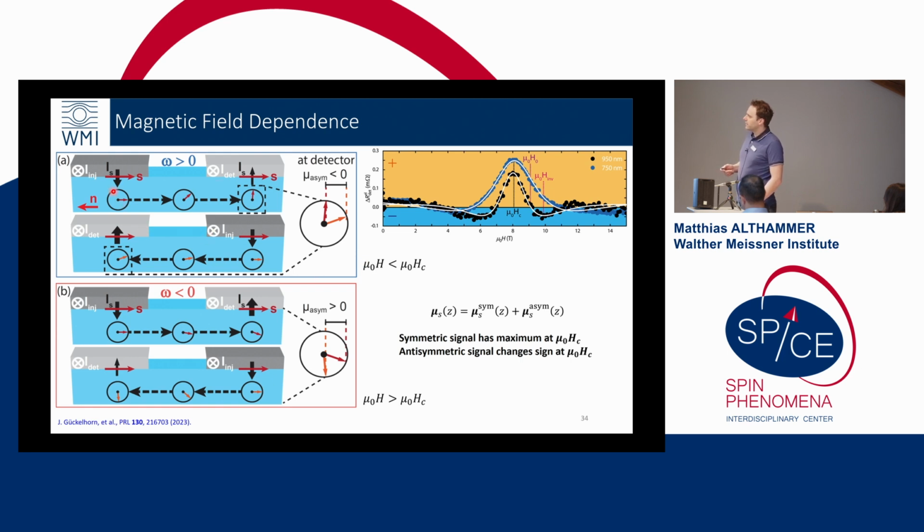On the one hand, we inject magnons on the left and detect them on the right, or you could change the experimental configuration, say, okay, I drive on the right-hand side and measure on the left-hand side. With this additional symmetry breaking in the magnon dispersion, the effective field that the pseudospin precesses through is different if you go from left to right than from right to left.